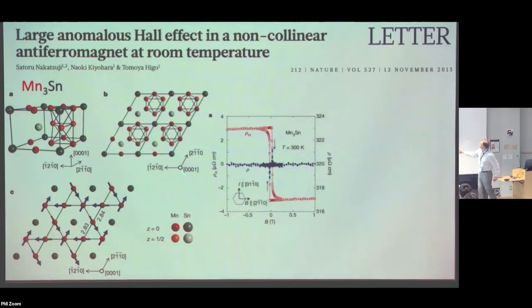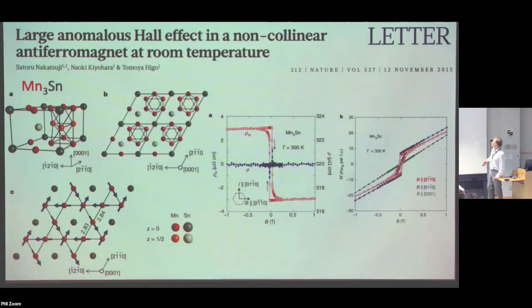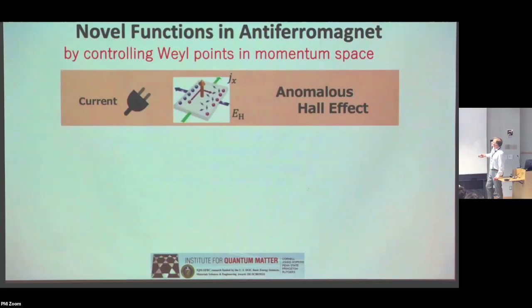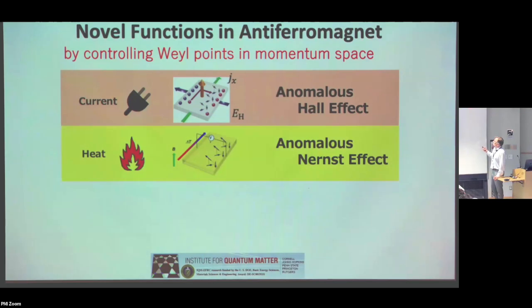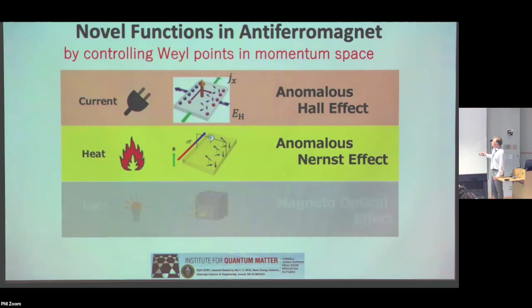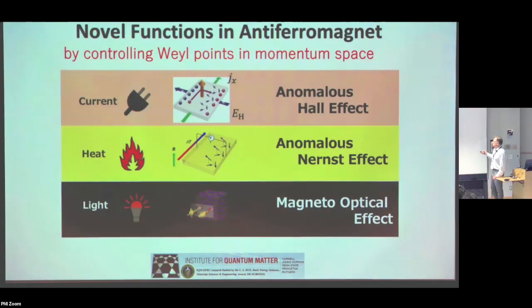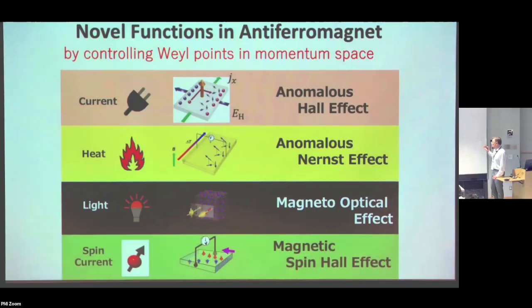So here you see the Hall resistivity as a function of field, and you have this little hysteresis loop. You can actually withdraw the field entirely and still have a Hall signal, which is either positive or negative. And of course, this brings many different applications, both in terms of the Hall effect and the Nernst effect. We also have an anomalous Nernst effect. There are very interesting magneto-optical effects. And there's a spin-Hall effect.